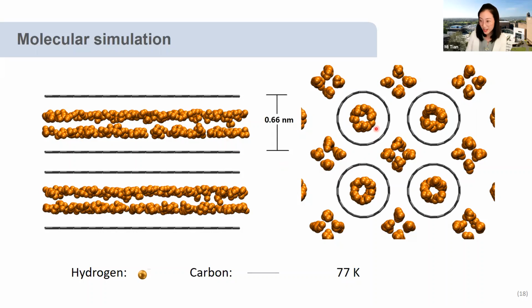On the other hand, in cylindrical pores with the same pore size, the packing of hydrogen molecules is quite different, as in this one. The hydrogen forms only one layer, and hydrogen also has some mobility inside the cylindrical pores. So that's the reason why the interaction between hydrogen molecules and the cylindrical walls is slightly lower than this one. That's why the hydrogen density inside single carbon nanotubes is slightly lower than in the slit pore shapes.